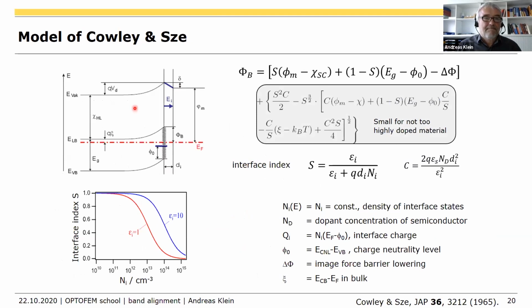And this is an empirical model to calculate that. So you have a semiconductor, you have a metal work function, you have some induced gap states with a charge neutrality level. I will explain later what a charge neutrality level is. If you do the electrostatics of this, you get this function. The barrier height is now given by S, our slope parameter, multiplied by the difference between the work function of the metal and the electron affinity. So this is the electron affinity rule. If S is 1, the Schottky barrier height will be this quantity. If S is 0, that means if you have Fermi level pinning, this will be the Schottky barrier height.